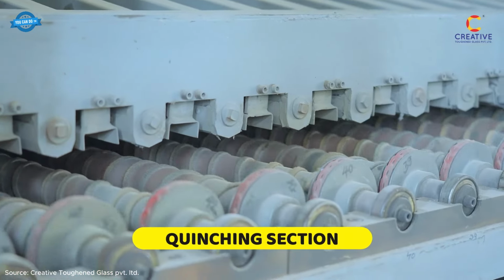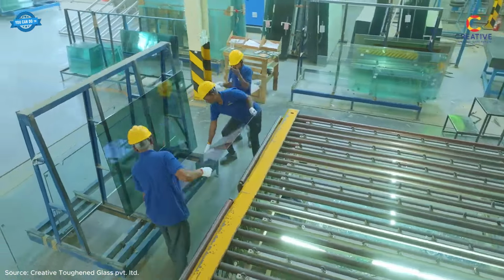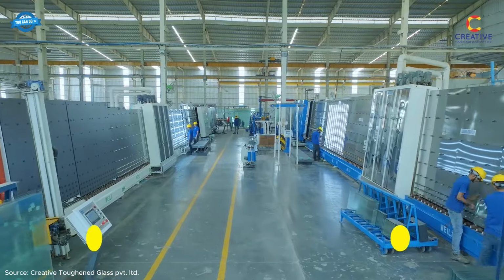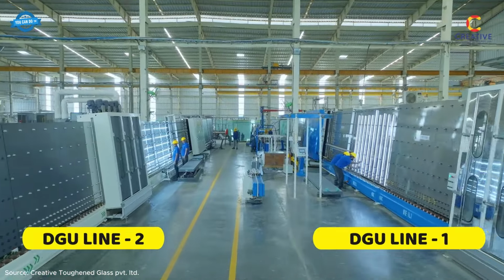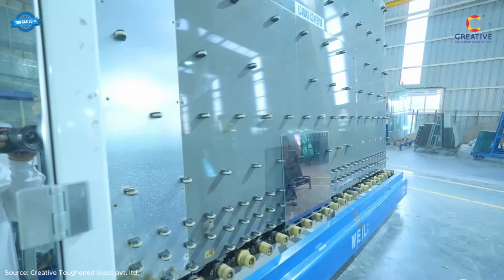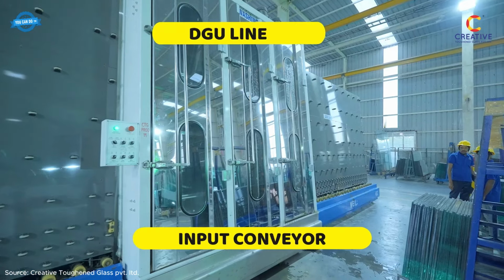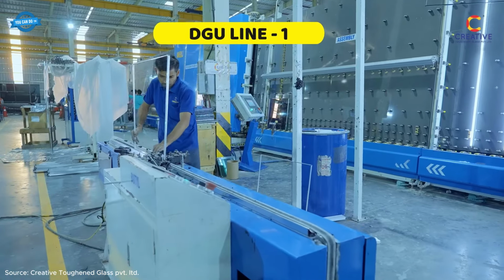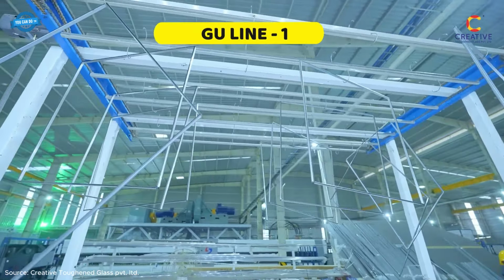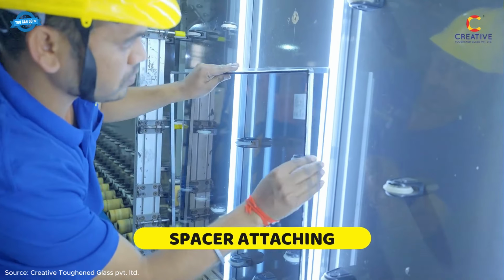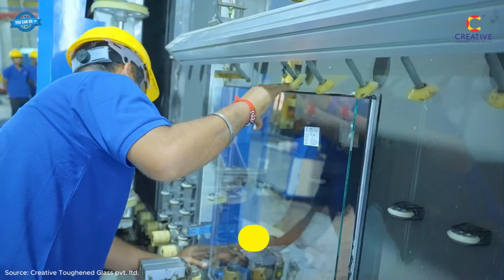The core operation takes place in the tempering furnace. Here, glass sheets are heated uniformly to approximately 700 degrees Celsius and then rapidly cooled in the quenching section using high-pressure air jets. This controlled thermal shock induces compressive stress on the surface and tensile stress in the core, significantly increasing mechanical strength and thermal resistance.